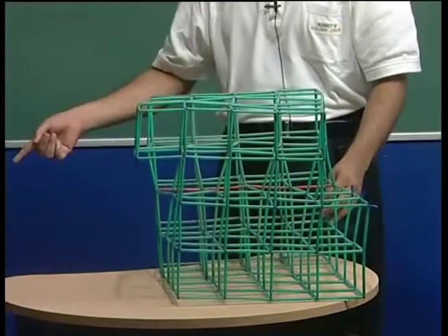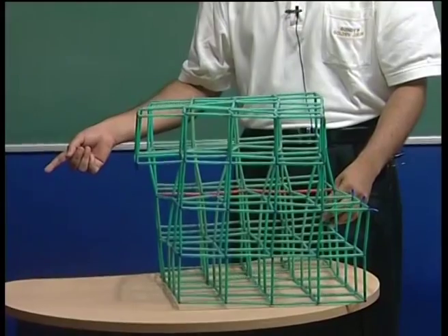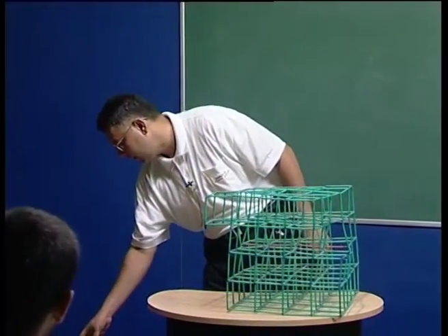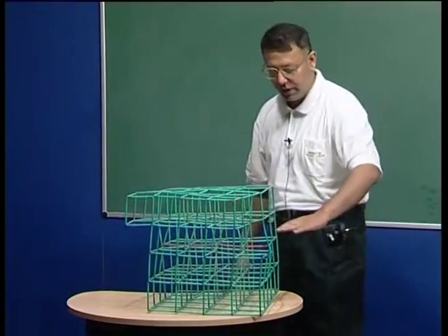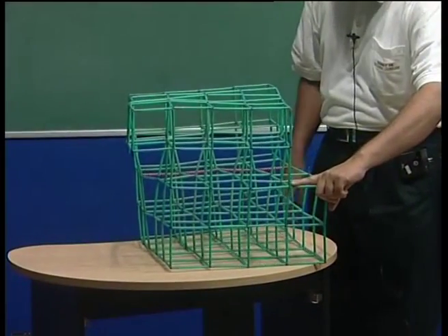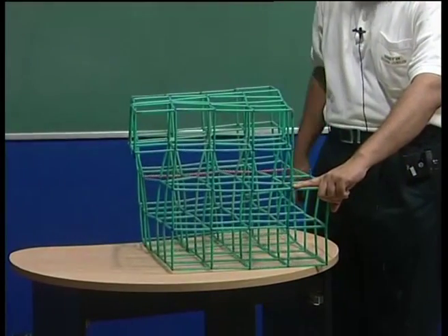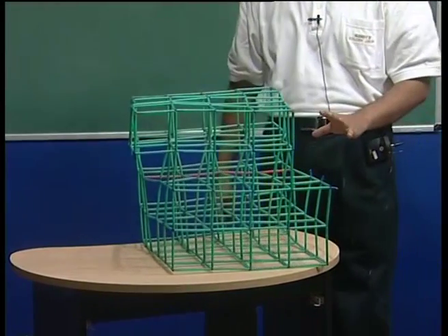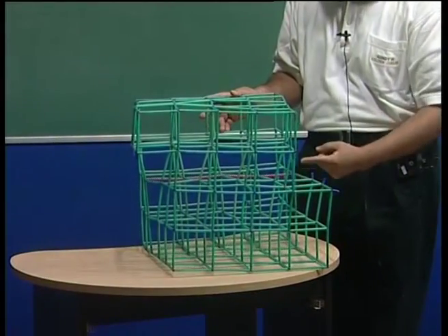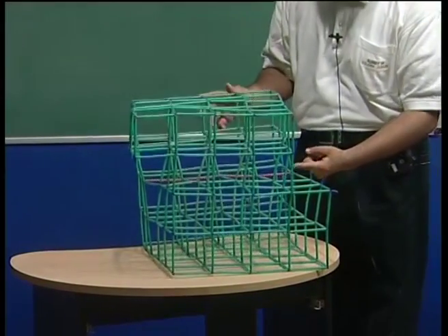In the case of the edge dislocation, the dislocation line was moving, of course, in the direction of the Burgers vector on the slip plane. Now this is my slip plane, and my Burgers vector is in this direction, but the dislocation line is moving perpendicular to the Burgers vector. So, this is an important difference between a screw dislocation and the edge dislocation.